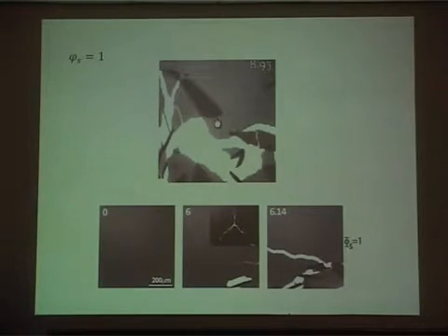But they also overlap between two flakes, and so you see dark regions. And this is the region through which light is coming out, the white region through which light. The two things that we found out of these cracks is usually you have Y-shaped cracks. And that's always true. You always tend to have Y-shaped cracks. These are disordered material. I mean, if I went up and plotted for you a G of R, it looks almost like a disordered material. So there is no order in the structure.